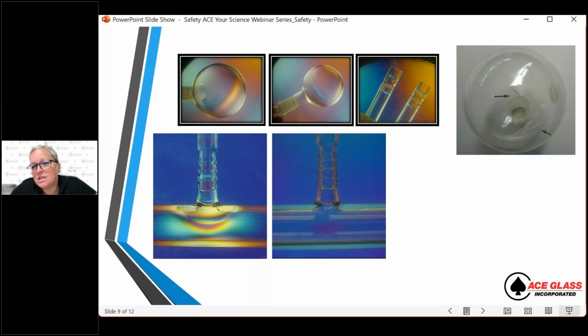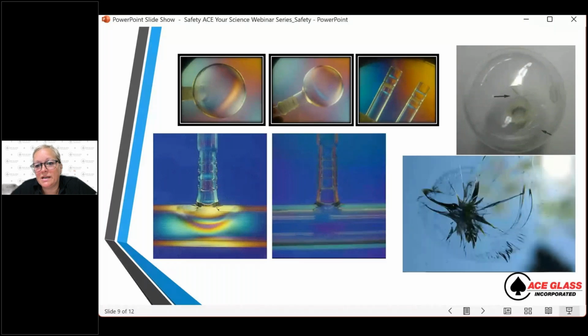Then also, I've showed these pictures earlier, but this is just a round bottom. You can see, I don't know if you can see my mouse index, but there are some cracks here. I also tried to put arrows on it so you can see it. And when you zoom in on that, those are star fractures. Sometimes people think, well, they look very small, it's all good, but really they can expand very rapidly, very quickly, especially if you heat it or you cool it, or you change the pressure, right? So this is very crucial. If you see a star fracture, ideally get rid of that glassware.